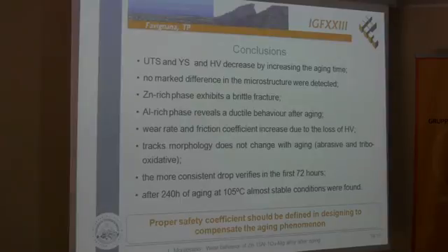So, concluding, we observe that the UTS, the YS, and the hardness of the material decrease with increasing aging time, showing that this material, as well as traditional alloys, changes its properties during the aging. The cause of this behavior is not related to the microstructure, as the microstructure doesn't change after the aging. But we observe that the material becomes more ductile, or in particular the aluminum-rich phase becomes more ductile after the aging, justifying the increase of the elongation and also the decrease of the UTS.